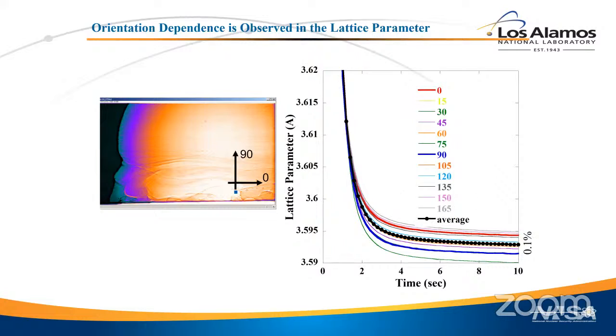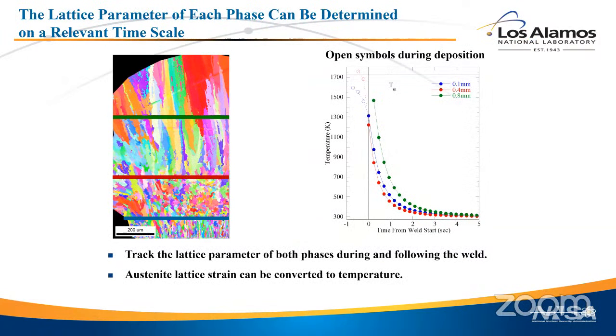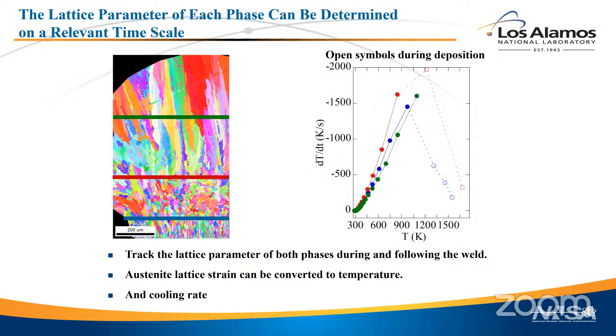So if you blow that spread up a little bit, you can see better the orientation dependence. So we get the temperature and we get the stress out of this as it develops. And we actually are getting enough temperature points. Our time resolution is sufficient to measure temperature as a function of time as it quenches, and then take the derivative of that, we can actually get cooling rate as a function of time. And that's important because it's the cooling rate that tells you how the chemicals segregate as you go through the liquid to solid phase transformation. So wire arc additive manufacture cools at about 1,000 degrees per second, which, if you read the literature 10 years ago, is kind of the estimate that you would expect. These are one of the first, possibly the first, internal measurements of what that cooling rate is.